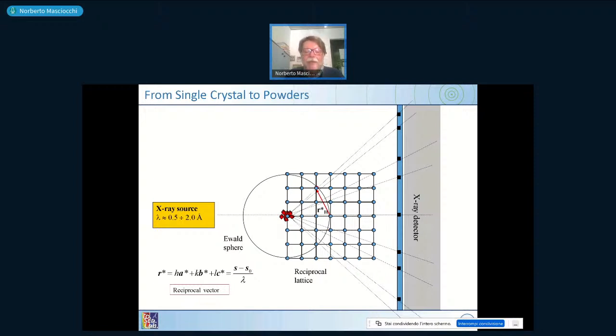Every single tiny piece originated from a single crystal, so it is itself a smaller but still ordered crystal. When you have a collection of these crystals which are oriented in all directions, you lose information on this vector R star, which is indicated in red, but instead you maintain its length. You're randomly orienting all the crystals in every direction, and all points which are at the same distance from the origin are kept at the exit point from the X-ray source towards the detector, so all these four lines you can see have the same distance. So even if only one or two of them were originally on the surface of a single crystal, more appear which are not on the surface, but will become on the surface when you have an orientational averaging.